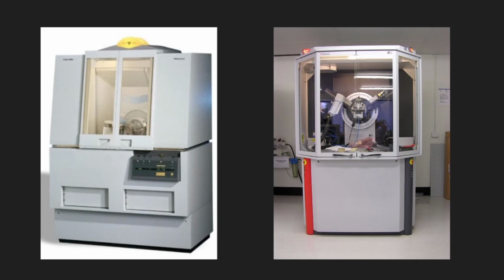So what you guys measure is the intensity for different crystals. What is the quantity that you guys measure? What is the thing that you guys are interested in? The structure factor, where it's the intensity. For different crystals, you can tell based on where the peak is, meaning the angle that you find it at, and then the intensity, meaning how many photons you're collecting at that angle. That will give you information about the crystal based on the two things that we defined earlier, which is the peak position and the peak intensity. You can use this graph with the intensity and the position to reverse engineer the structure factor, and from there the HKL values. And the HKL values basically define your lattice.